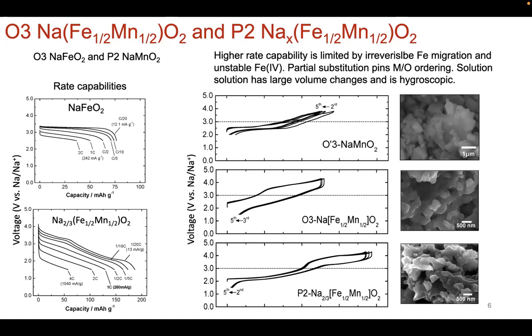What you see here is the existence of plateaus that you don't see in layered materials for lithium-ion batteries, right? So there's sort of a plateau here, and yes, it does slope all the way through. So I guess what we have to do is corral our discussions and tailor our arguments to a specific range of capacity. What you see here is what we've seen in lithium-ion battery cathodes that aren't layered, like Mn2O4, where we see the phase transformation jump, and the voltage jump there too.